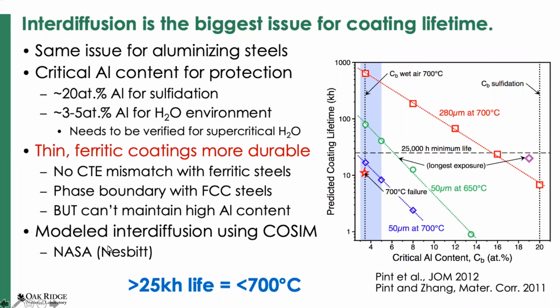Again, these are predictions made based on some experimental inputs that we plugged into the COSIM model that NASA developed, Jim Nesbitt. And so you can see that 700 degrees C is a tough goal. If you drop that down to 650 degrees C, then you get sort of an order of magnitude increase in your lifetimes, and maybe you're going to get a little bit longer life. But again, for steam environments or combustion environments, you need a lot lower aluminum content, kind of the shaded area here. And here's our prediction, and here's actually a coating failure. So we're not too far off with the model. But again, we're just modeling interdiffusion. You don't really even have to model the environmental effects.